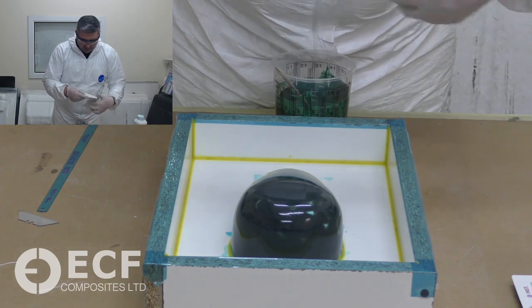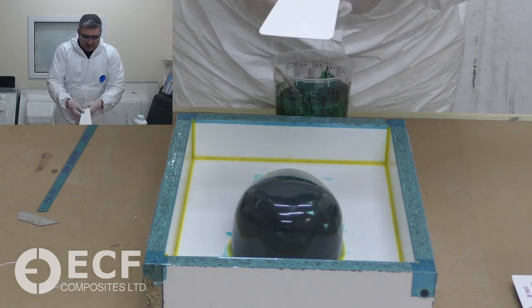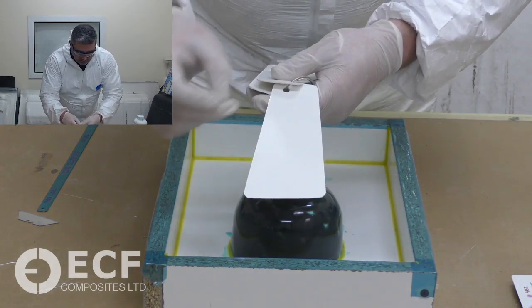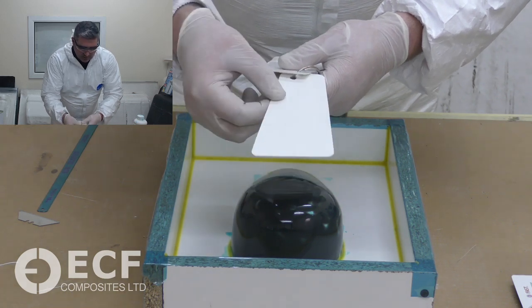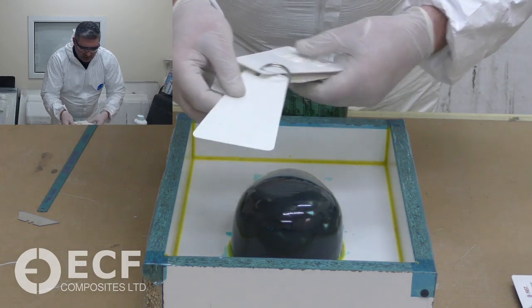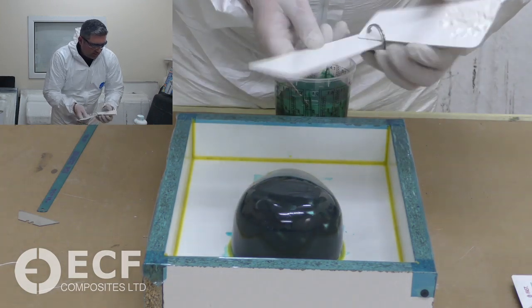Also, if your gel coat doesn't cure properly and it's quite soft, I don't think the camera can pick it out, but you sometimes get the strands showing through the part as well. So you need to make sure your gel coat's nice and hard before you start laying it up.